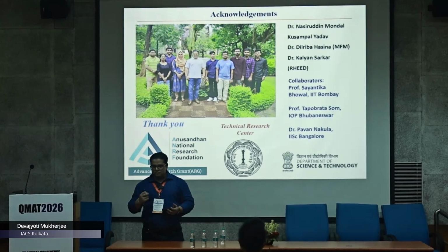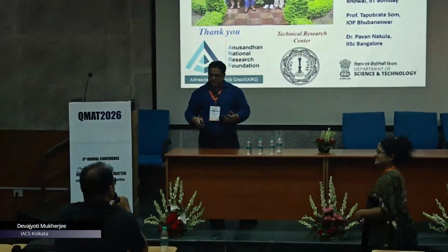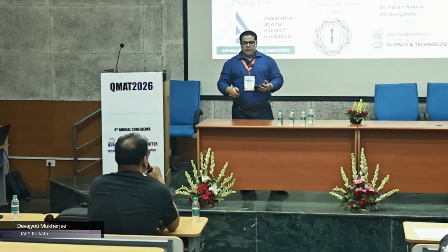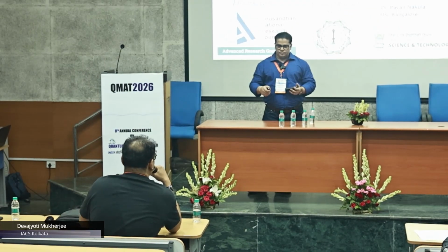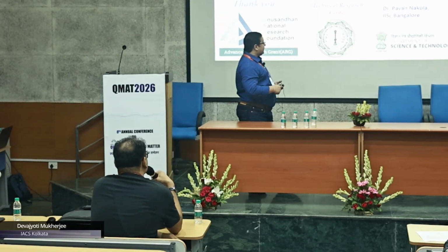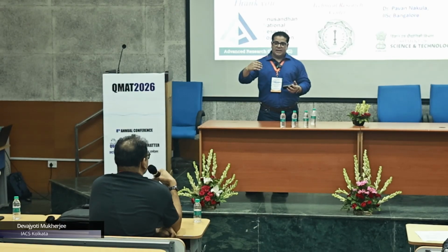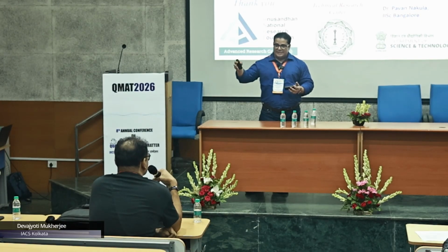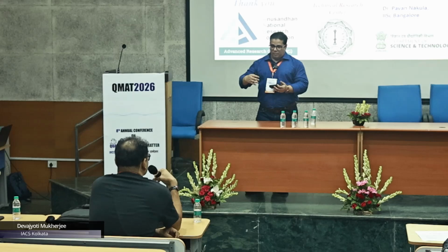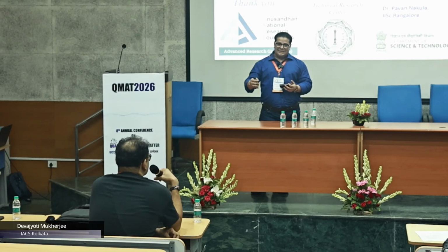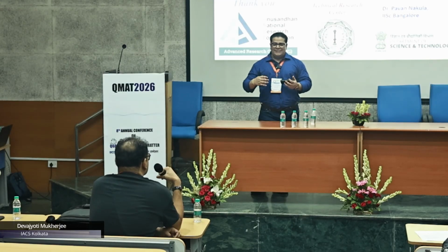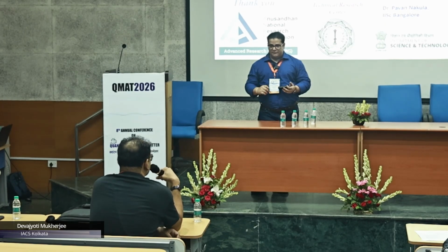Just I was wondering, have you come across oxygen vacancies in all these samples, and what is the role of that? Because the properties should be highly dependent on it. So basically, we could not detect oxygen vacancies in most of these samples. Oxygen vacancy changes the conductivity of films because it's a charge center. That is a separate study in itself. But typically in these kinds of materials, oxygen vacancy is something you cannot avoid. But its role is not that significant compared to the magnetic properties that we are studying. In terms of transport, it's not much different, yes.